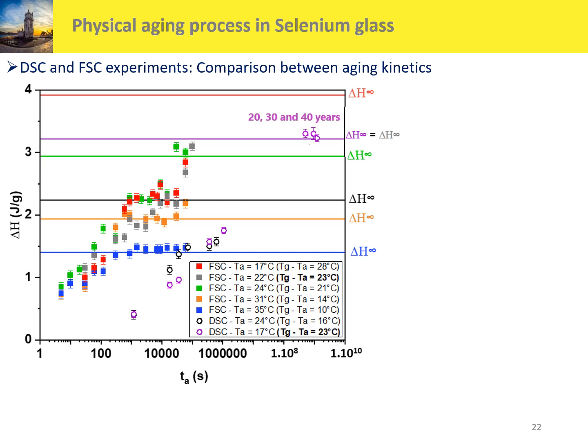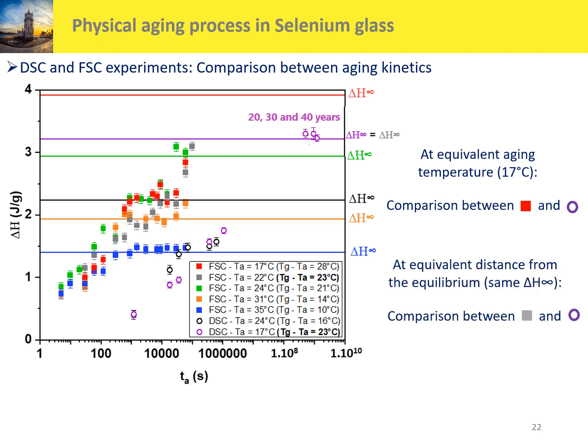Finally, we compare the aging kinetics between differential scanning calorimetry and fast scanning calorimetry experiments. For this goal, we have in fact two ways of comparison. Indeed, we can work at equivalent aging temperature. So in our case, we choose 17 degrees C as aging temperature for the two kinds of experiments. So we have to compare the red squares and the purple circles on this graph. But we can also work at equivalent distance from the equilibrium. It means that in this case, we have the same value for delta H infinity. And for this comparison, we have to compare the gray squares and the purple circles.